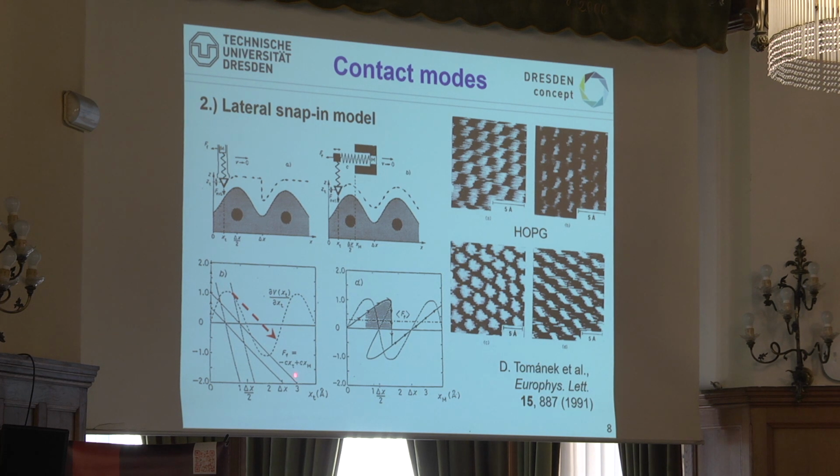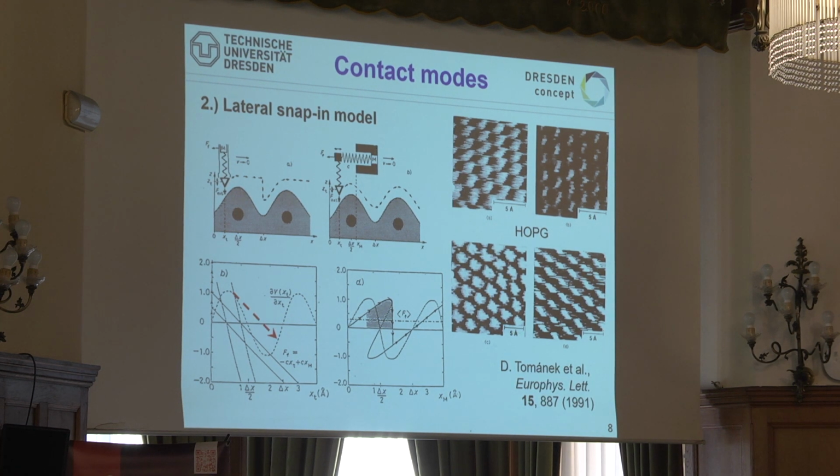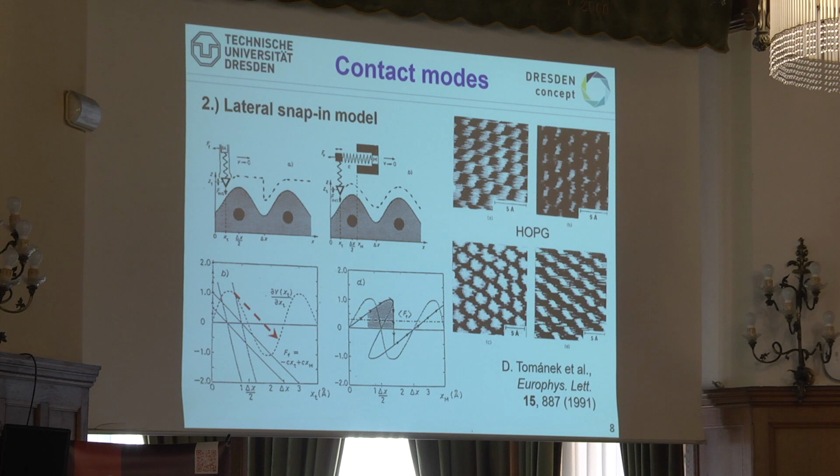You see, this is a force-distance plot, which means this dashed line, that arrow, is my K constant for the torsional mode. It's my torsional K constant. And you see nicely that we have this instability, jumping from this point exactly to this point, which means in energy we go up, and then bang, you go down, up and down. So that's exactly what happens on the atomic scale.